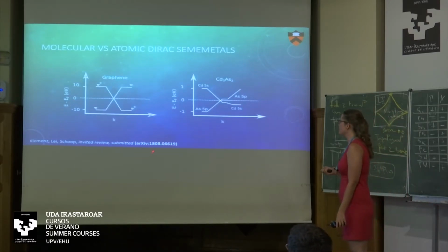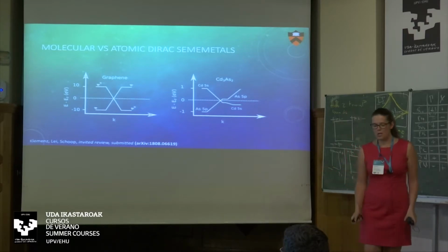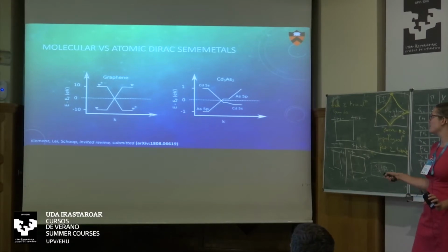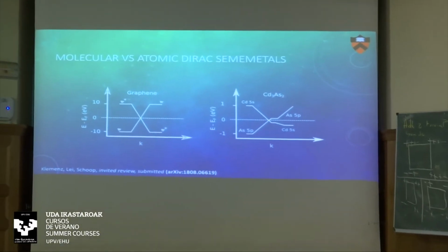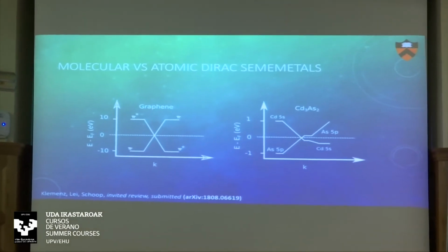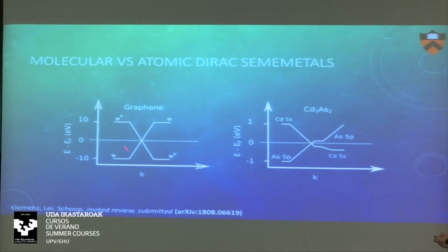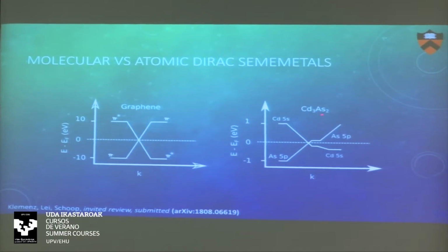First, I want to differentiate that graphene is, in my point of view, a different type of 2D Dirac semimetal, or whatever Dirac semimetal, than cadmium arsenide and the other known ones. Because in graphene, I just said it's the pi bonding which causes the linear dispersion and the band inversion. So the bands are inverted here between pi star and pi. So it's actually a bonding which causes this. Whereas in cadmium arsenide, and I'll show you later, it's actually just a low-lying s electron of cadmium.